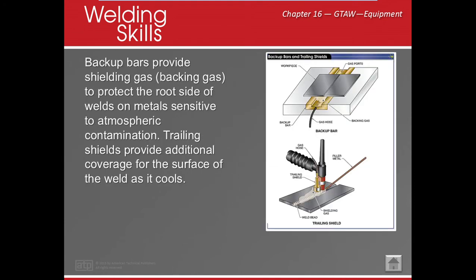All right, what do we have here? We have backing bars. This is a backup bar, and what happens is we put our gas into here, and there's little holes cut into it so that we can make sure that the backside of our root weld, especially when we're doing open root with TIG, is protected. Well, what happens if we don't? We're going to get what's called sugaring or black candy. It's ugly, it's nasty, it's gross, and it's contamination. So we use a back gas, and it protects things from atmospheric contamination.